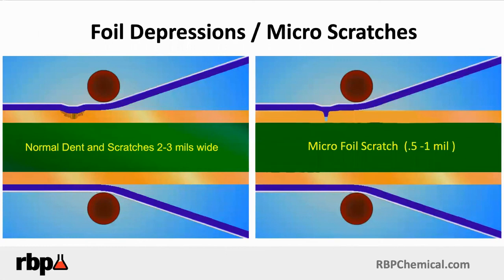Here's a good example, a schematic. Here you see your copper foil, your layer. This is your copper, this is your laminate. Here is your hot roll laminator, both the top and bottom. These are your rollers. And this is your photoresist being applied to both sides through the process of hot roll lamination in the photoresist area. And you can see that it's very important that the photoresist conforms to the surface. Here's a little dent here. It's just showing you that with normal dents and scratches, you expect to have some situations like that, and you want to ensure that the photoresist does properly adhere. Because otherwise, if this is a significant dent and scratch like you see here, that's pretty deep. Good chance that the photoresist never actually makes contact with the copper surface all the way down here.